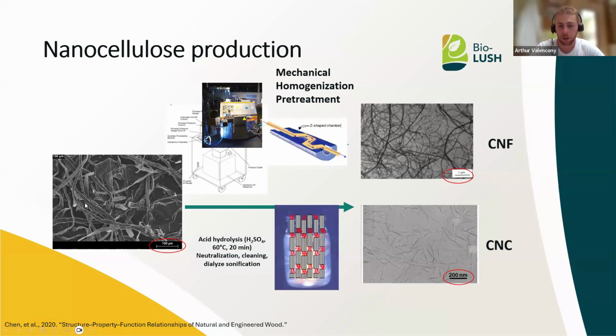a pulp suspension that can be mechanically pretreated to decrease the fiber length. And then this pulp suspension, we can introduce into a homogenization step with or without a pretreatment before. So here we can see a homogenizer, which is a device which will defibrillate the fibers by pushing them into a small gap at really high pressure. It can go up to 1,500 bars, or we can have this microfluidizer with a Z shape, which will also defibrillate the fibers.